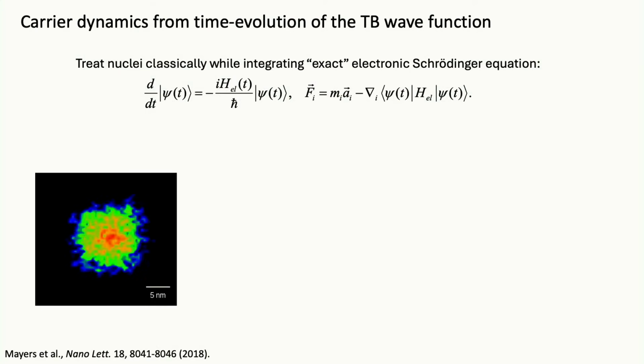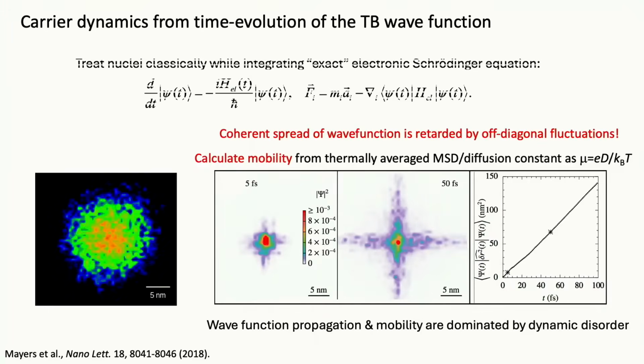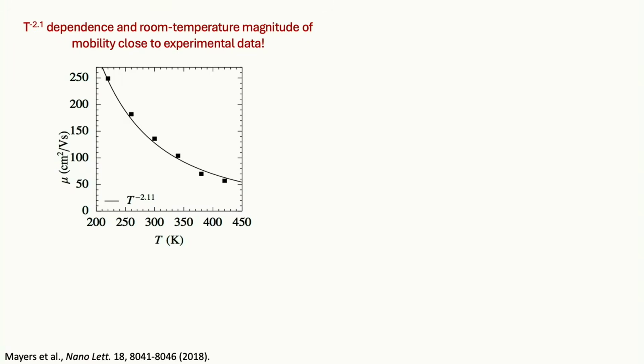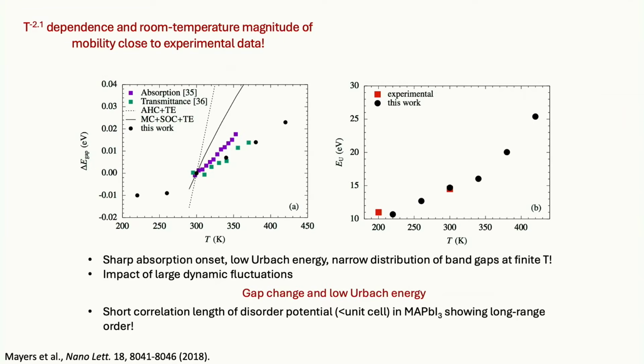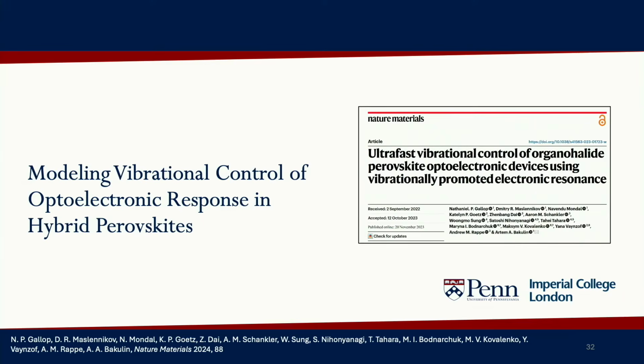Okay, so what we do is we have this tight binding model. We actually solve a one electron Schrodinger equation. We say, how fast will an electron spread out? If it's initially here, how fast will it go somewhere else? And we're actually able to calculate the mobility and the temperature dependence of the mobility, and this agrees with experiment. And so this was the first time that this was done, and it's based on this model of including the distortions in this floppy, soft, hybrid perovskite lattice, and understanding why and how that makes it good for photovoltaic applications.